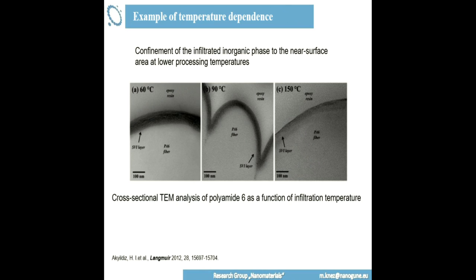So please be aware that the precursors, in many cases, will be able to diffuse into your polymeric substrates. And if you don't want to have this, you need to react appropriately. That means you need to set up your process parameters in a way that you avoid as good as possible this infiltration. Unless you, of course, want it. If you want it, you can have many benefits out of here.